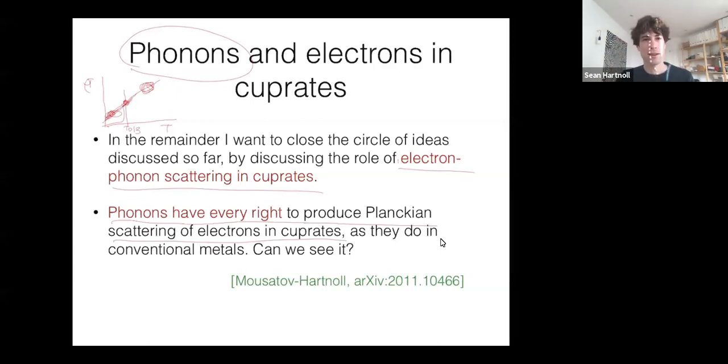And so there's actually a bit of a paradox in the cuprates: even if you believe that quantum criticality is causing the scattering, the phonons should also be scattering. And this phonon scattering should appear at about this scale, and just add, because a particle can bump into different things and the scatterings add. That is just not seen, and that's a quite confusing thing. So we're going to think a bit about this. Why don't we see it?